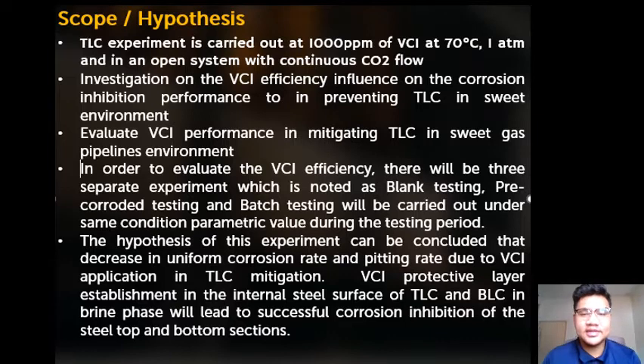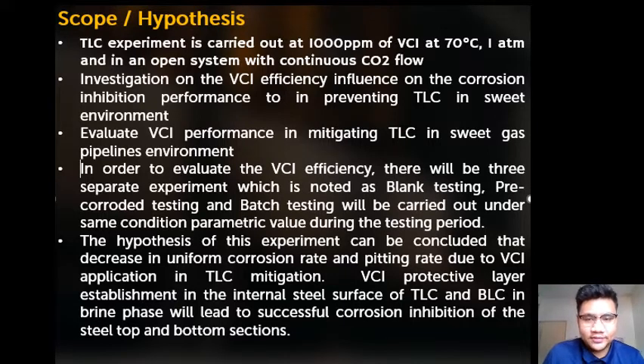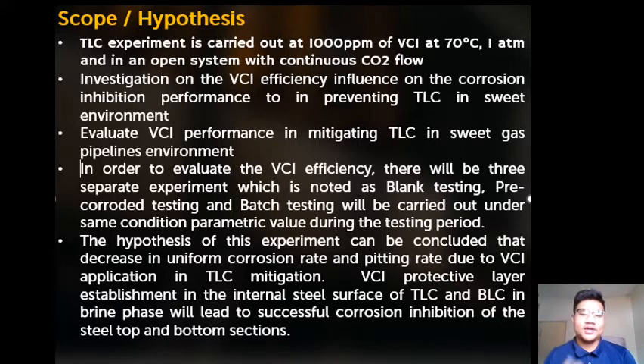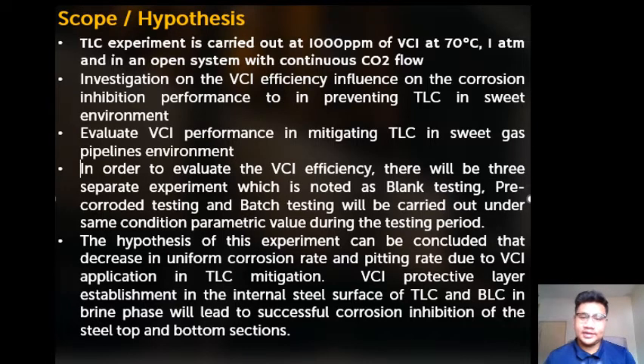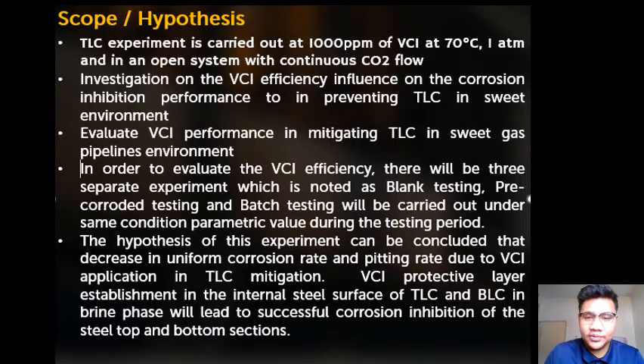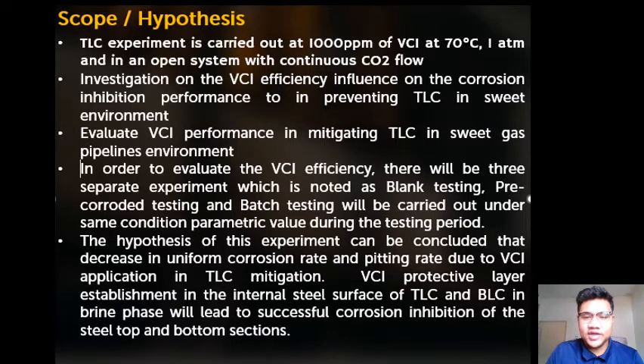For this experiment, the TLC experiment is carried out at 1,000 ppm of VCI at 70 degrees C, 1 atm in open system with continuous carbon dioxide flow, which creates the sweet environment. This experiment is to evaluate the VCI efficiency in mitigating TLC in sweet environment. Three separate experiments with the same parametric value will be carried out for a five-day testing period: blank testing where no VCI is injected, which is the control of the experiment; pre-corroded environment; and batch injection. The difference is that pre-corroded VCI is injected on day one, while batch injection has VCI injected on day zero, right after equipment setup. The hypothesis can be concluded by observing the change in uniform corrosion rate, pitting corrosion rate, as well as the surface structure and morphology of the steel sample.